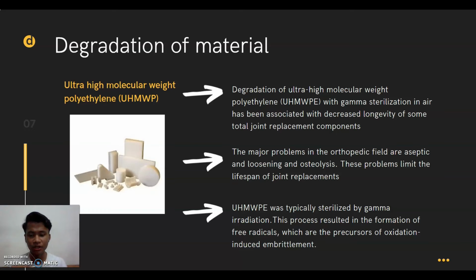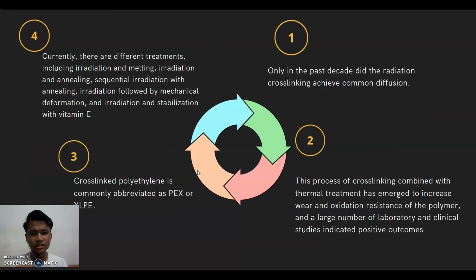When sterilized by gamma irradiation, this process results in the formation of free radicals, which are the precursors of oxidation-induced embrittlement. Only in the past decade did radiation cross-linking achieve common diffusion. This process of cross-linking combined with thermal treatment has emerged to increase wear and oxidation resistance of the polymer, and a large number of laboratory and clinical studies indicate positive outcomes. Cross-linked polyethylene is commonly abbreviated as PEX or XLPE, and currently there are different treatments including radiation and melting, irradiation and annealing, sequential irradiation with annealing, irradiation followed by mechanical deformation, and irradiation and stabilization with vitamin E.